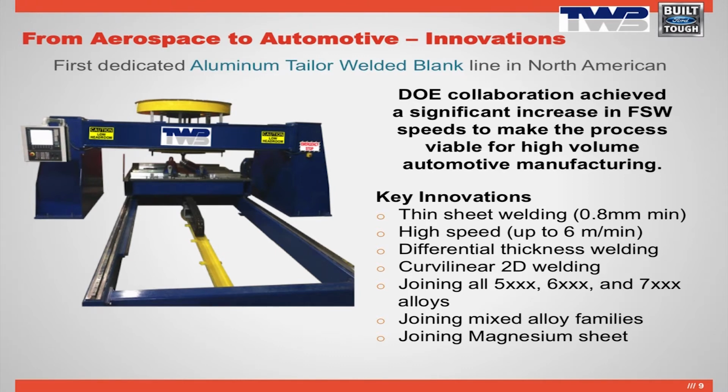Through a Department of Energy collaboration, these technical hurdles have recently been overcome. The collaboration resulted in the commercialization of high-speed friction stir welding. Whereas only several years ago, speeds of 1 meter per minute were common, speeds of 6 meters per minute are now obtainable. Also, sheets as thin as 0.8 millimeters have been successfully joined.